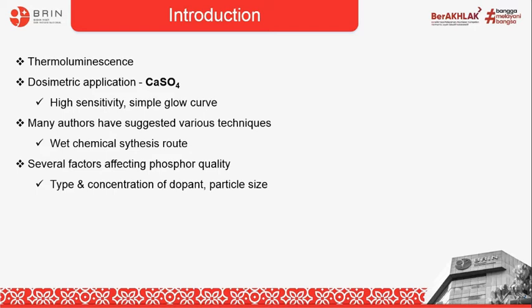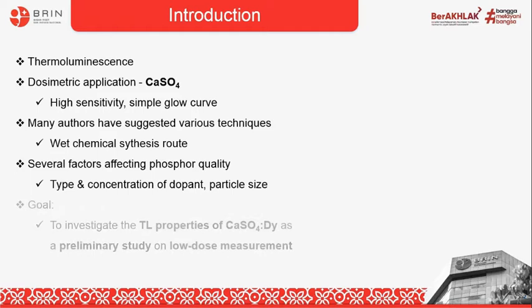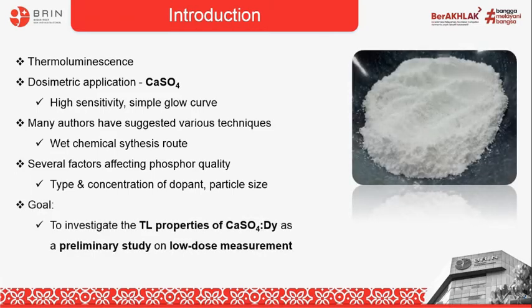The particle size itself is dependent on the manufacturing process, so controlling variables such as precursors, acidity, reaction time, and calcination temperature is important to obtain the desired particle size. In this work, we investigate the properties of dysprosium calcium sulfate TL material, and dysprosium was introduced as the luminescent center at certain concentration. This work serves as a preliminary study for our research group to obtain TL material regarding the application of low-dose measurement.